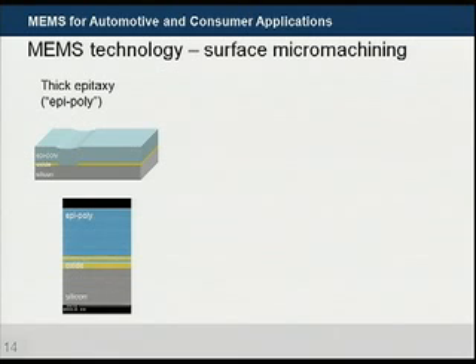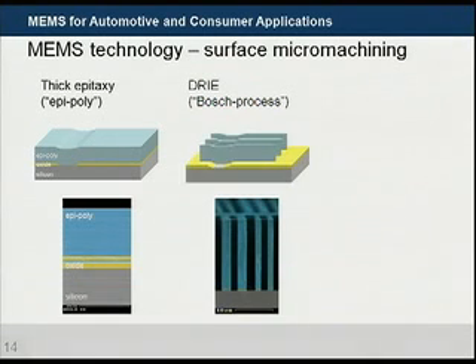We take the silicon substrate, deposit a sacrificial oxide, shown in yellow on these cross-sections, and onto this a thick poly. This is mostly deposited in an epitaxial reactor, so we can achieve high deposition rates and have a very good mechanical material. The typical thickness is 10 or 20 micrometers. The next step is to etch the mechanical structures by etching into the depth by deep reactive ion etching, and very perpendicular walls with high aspect ratio and very good lithography deposition precision can be made by this process.